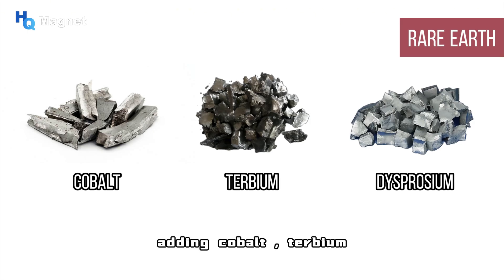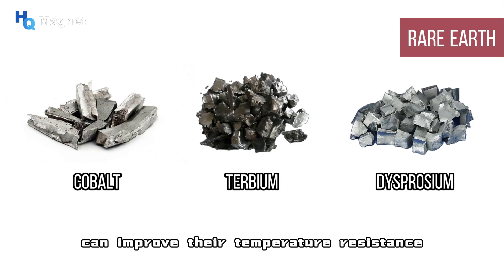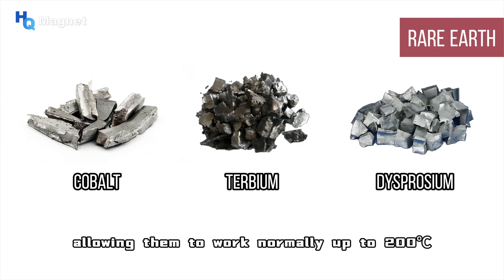Adding cobalt, terbium, dysprosium, and other elements to sintered neodymium magnets can improve their temperature resistance, allowing them to work normally up to 200 degrees Celsius.